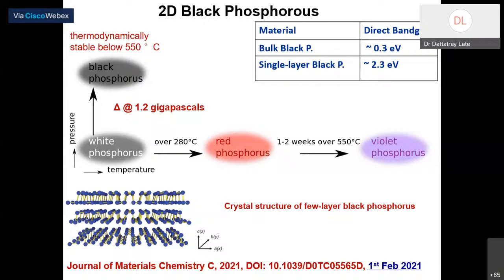So another material which is known as 2D black phosphorus. Why is it called black phosphorus? Because it looks black in color. You see, the natural phosphorus which is available in nature is white phosphorus. If you heat it to 280 degrees Celsius, it converts into red phosphorus. And if you keep it under the same condition for 1 to 2 weeks at 550 degrees Celsius, you will be able to convert it into violet phosphorus.